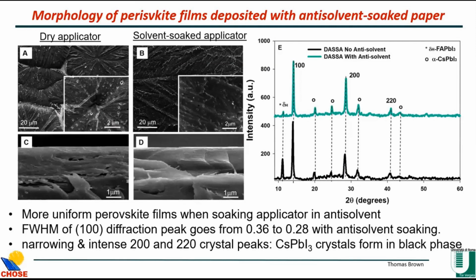This is SEM. So this was drawing with a normal piece of paper, and here it was drawn with a piece of paper applicator soaked in anti-solvent first. You can see here there's some cracks, much more uniform with the anti-solvent. And also here you can see that nice crystals are uniform throughout the thickness of the layer. So it helps the charge carriers go from one end to the other without encountering too many grain boundaries, which of course act as recombination centers. So the morphology certainly improved.